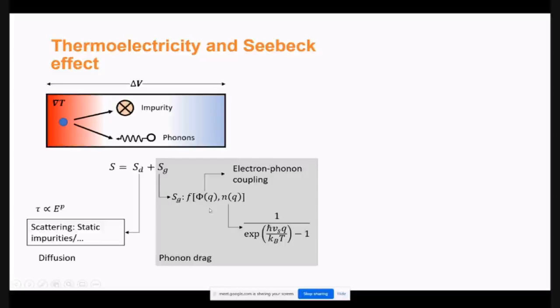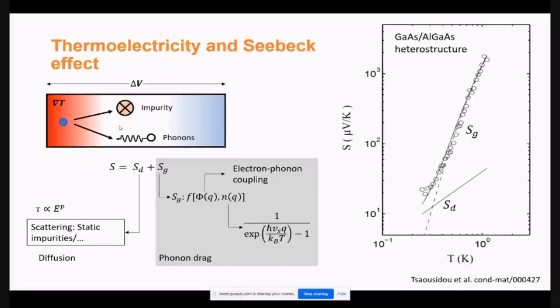phonon drag, SG. Okay, so the phonon drag is essentially given by the occupation number of phonons, obviously, because how many phonons you have will determine what will be the voltage difference that you can create between two ends. Okay, and then the diffusion thermopower is, of course, because of the static impurities in the system. If you take a look at a gallium arsenide kind of system or any other semiconductors, then the phonon drag essentially dominates the thermoelectric power in most of the temperature range down to millikelvin.